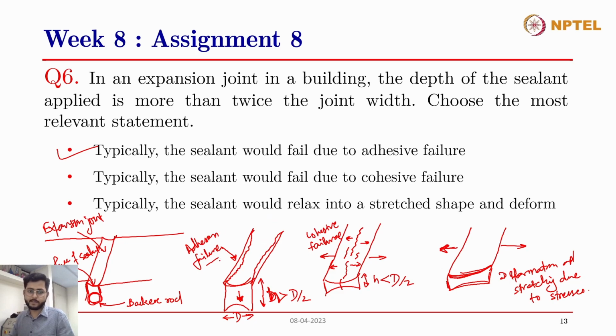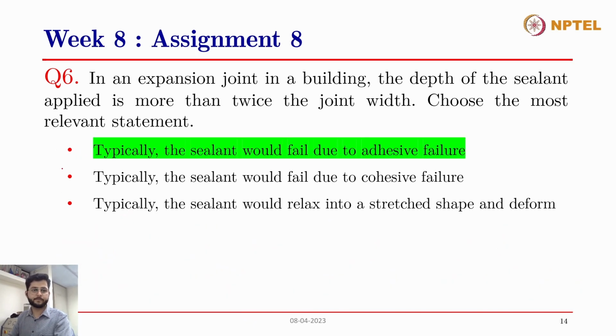But in this case, what is mentioned is the adhesion failure because the depth of the application of the sealant is more than twice the diameter of the backer rod or twice the joint width, and therefore this will create a situation where the sealant will peel off from the concrete surface and there will be an adhesion failure. There will be debonding of the sealant from the concrete surfaces on both the sides. So this is a case of adhesion failure, right?